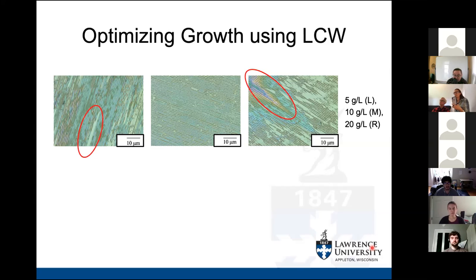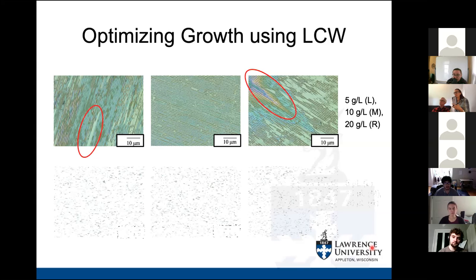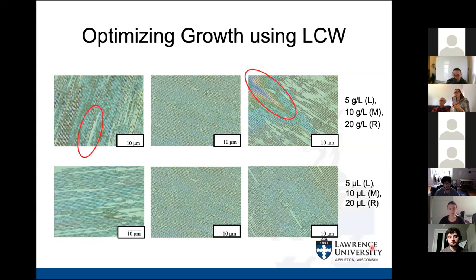Once the concentration was optimized, I tested the drop size using the 10 grams per liter concentration. Since the syringe we used to drop solution onto a substrate was a 100 microliter syringe, I tested 3 drop sizes: 5 microliters on the left, 10 microliters in the middle, and 20 microliters on the right. The reason I didn't test drop sizes greater than 20 microliters was because those drops would be so large that they would run off the substrate once the PDMS stamp was pushed down onto them.